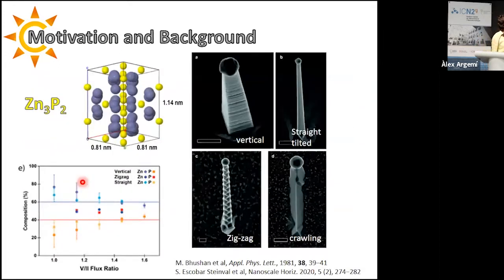The material we investigated for this purpose is zinc phosphide, which possesses a tetragonal unit cell, here depicted. As we can see, the C-axis is much bigger than the other two axes. This type of material was proposed for solar cell application almost 40 years ago, finding a very low efficiency of around 6%. The main reason for this is the challenge of growing this material on the currently available substrates, because with such a big unit cell, it's difficult to find a material where it can easily adapt.